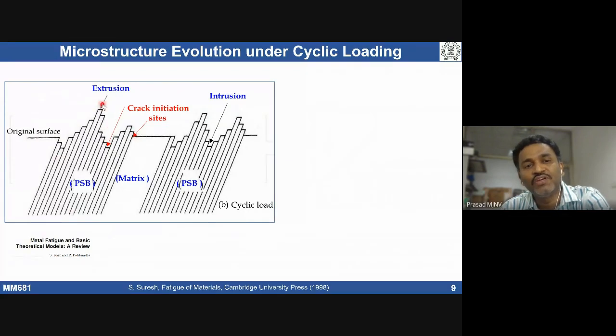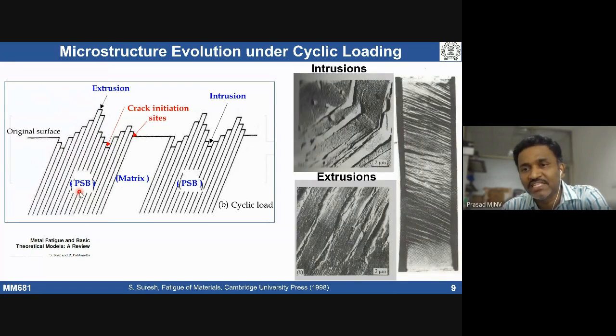The formation of intrusions and extrusions can eventually lead to persistent slip bands at high magnifications. If you go to high magnifications locally, I do see formation of persistent slip bands in the material. If I take a tensile specimen and polish it very nicely, and then do cyclic slip activity, I see formation of these marks on the surface. If I go to a little higher magnification, I see valleys and hills.